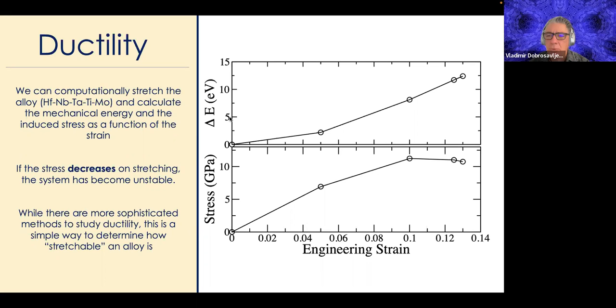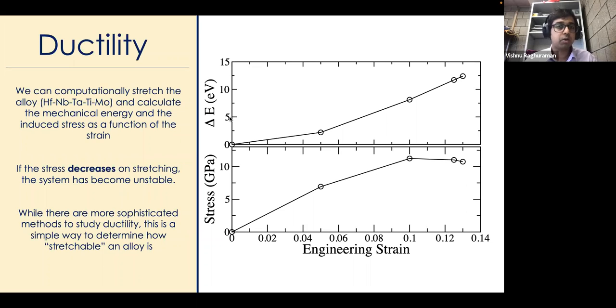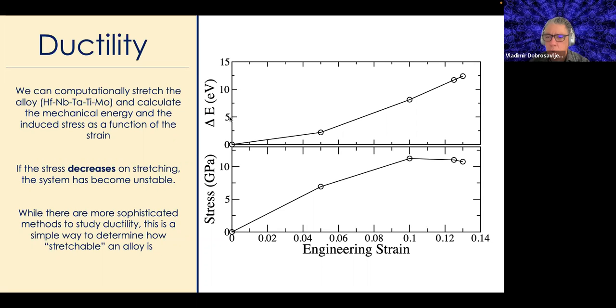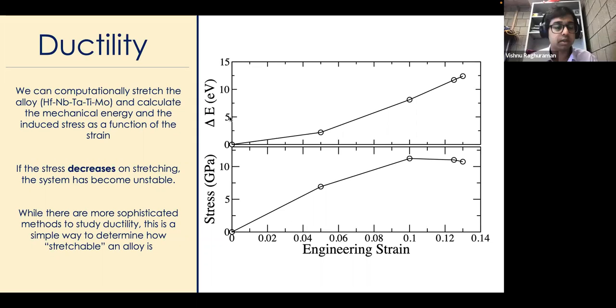But do the atoms remain periodic, or are you allowing some defects to be generated, like dislocations? We are allowing, so they don't have to be periodic. And often there can be quite a bit of lattice distortion. So is this a supercell calculation? How big is the supercell? Yes, these were done with a 128 atom supercell.